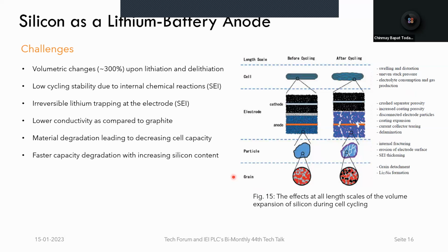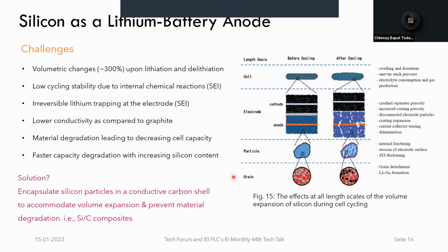So what is the solution to this? Because we want to use silicon, but it has these problems. One of the research approaches is to encapsulate or cover these silicon particles with a conductive carbon shell to accommodate the volume expansion, prevent the material degradation, and improve the conductivity. And that is the formation of silicon carbon composites.